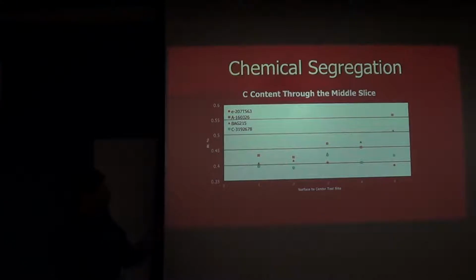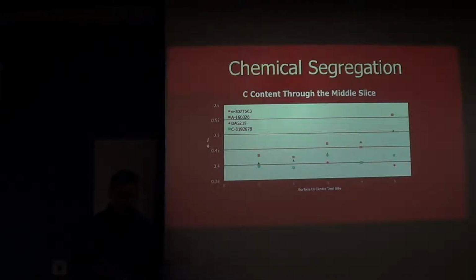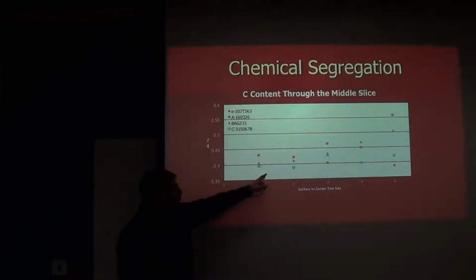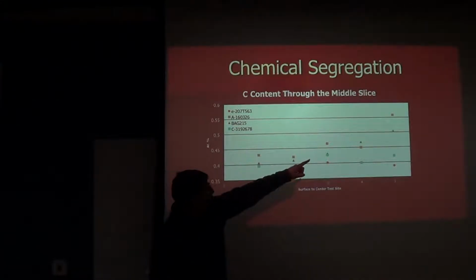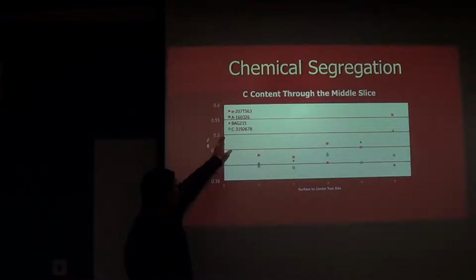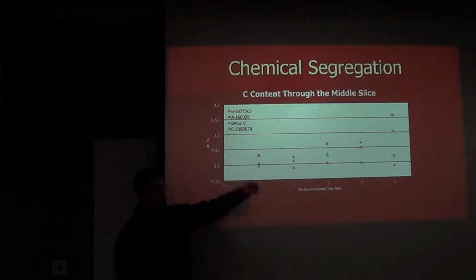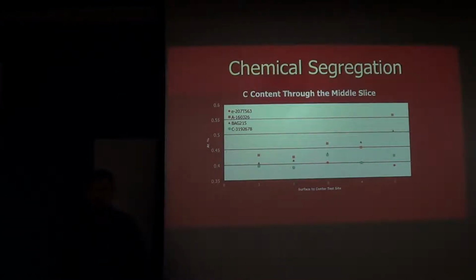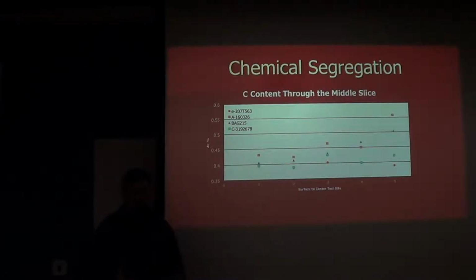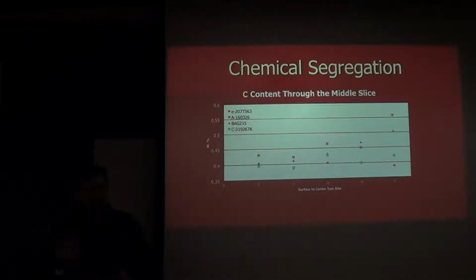This one does show the summary of the carbon content. So we were dealing with material that was nominally a 4140, so approximately 40 carbon material. And we could see that it really quickly changed. All the way out the center line, we had some carbon that was up in excess of 55. That's a huge difference. You think about the effect of carbon on hardenability, which is something that we'll cover in another lecture, but some of you may have been exposed to it already.